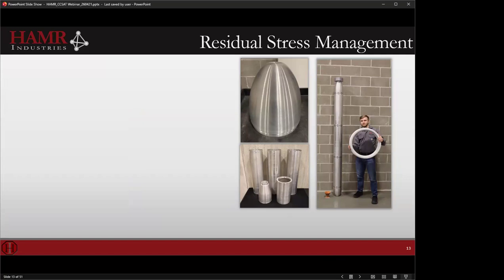So again, every manufacturing modality has to manage residual stresses. There's stress risers and thick to thin transitions. It's a challenge in castings, forgings, it's a challenge in additive. So on the right here, we've shown that we can make large parts. We can do it repeatedly and reliably. Those are 6 3/4 diameter on the bottom, several feet long, and then you see the top. That's in the realm of around 13 inches and about 1.5 feet or 2 feet.